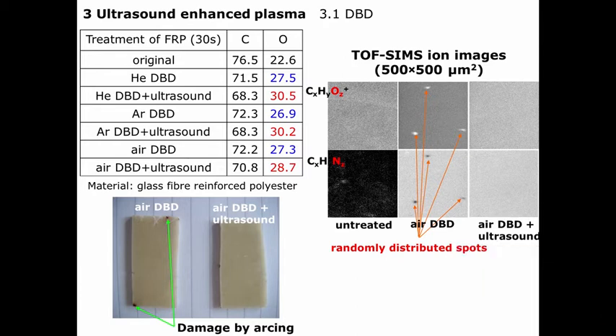And also, it is known that surface can be uniformly treated. Some heavily oxidized spots can appear with air DBD. But with ultrasonic irradiation, the surface became very uniformly treated.